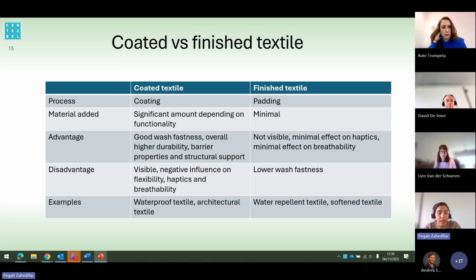For example, if we apply polyurethane as a coating, then we will have a significant amount of the formulation on top of the textile, and it will have much higher durability and barrier properties for the textile. But on the other hand, it will be a visible coating on the textile, and it will have some negative influence on the flexibility and breathability of the textile. Some examples of this kind of application are waterproof textile or architectural textile.